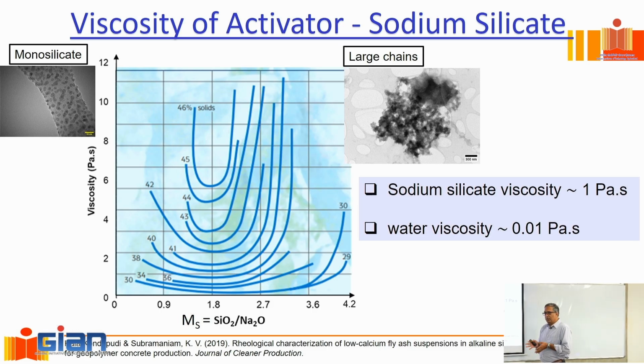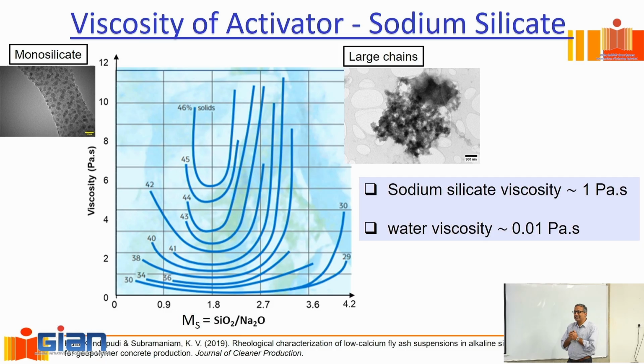Okay, so the viscosity of the activating solution itself now depends upon the MS of the solution. Now I've added another complication to the whole story. Remember, I'm going to take this activating solution and mix it with fly ash or slag or a combination of the two. Now, just to give you an idea, typically, when you look at sodium silicate, it is much, much more viscous compared to water.